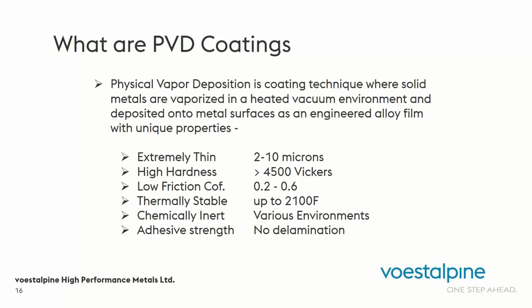Now, one thing that's extremely important is adhesive strength. Coatings do not absorb into the surface. They basically stick to the surface of the tool. But the important aspect of this is that they don't delaminate. Okay, they have very high adhesive strength. Unlike maybe what you've seen with hard chrome. Hard chrome after a number of cycles will start to delaminate from the surface of whatever part you're using it on. This doesn't happen with PVD coatings, but it will eventually, like anything else. It is a sacrificial layer, and it will wear through it.